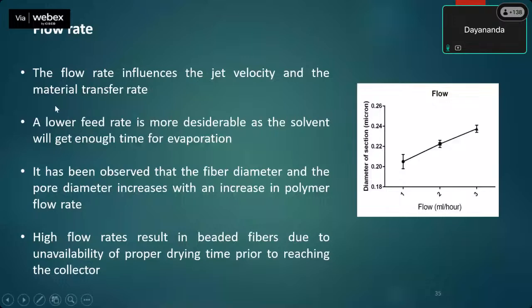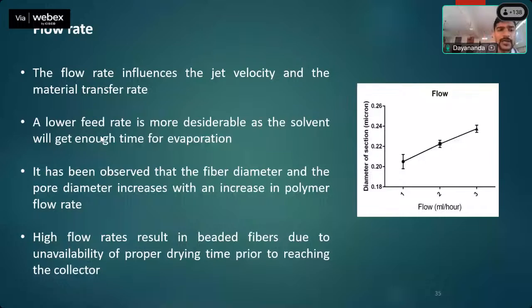Flow rate influences the jet velocity and material transfer rate. A lower feed rate is more desirable, as I mentioned. We generally keep the flow rate very low because it is desirable so the solvent gets enough time for evaporation. If you keep the flow rate very high, the solvent along with the polymer solution will not get sufficient time to evaporate. So to get a proper nanofiber mat, the flow rate has to be fixed properly, as it results in proper fiber formation.